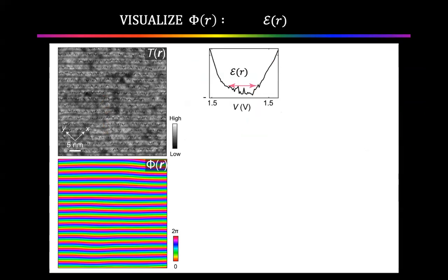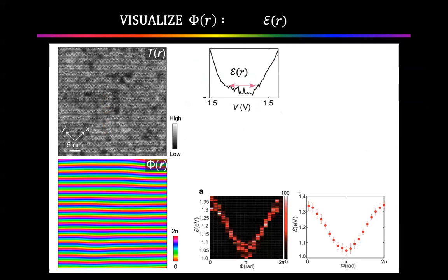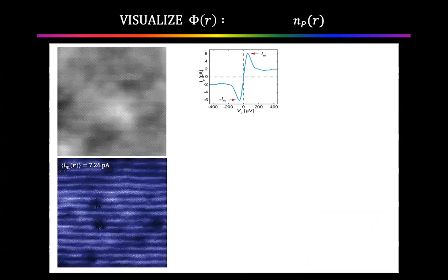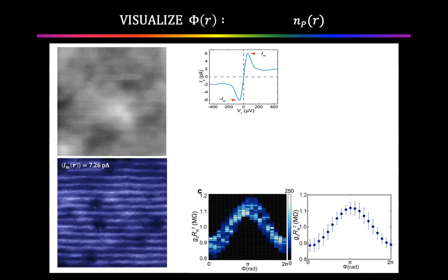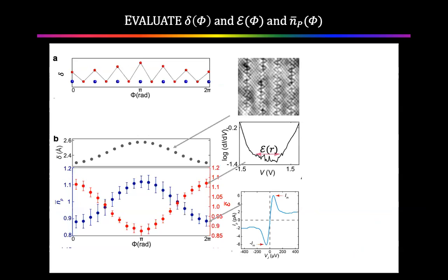What that means is, for a given field of view, we know the charge transfer energy at every location and the phase at every location. We can map the charge transfer energy as a function of phase and average that over the whole sample to get charge transfer energy as a function of what's happening to the unit cell due to the modulation. Similarly, we measure the Josephson current as a function of phase of the modulation. Map that over the whole field of view, and that tells us what's happening to the electron pair density throughout the modulation. So we can combine all those three things together: apical distance in one period of the modulation from here, charge transfer energy in one period of the modulation from here, electron pair density in one period of the modulation from here.